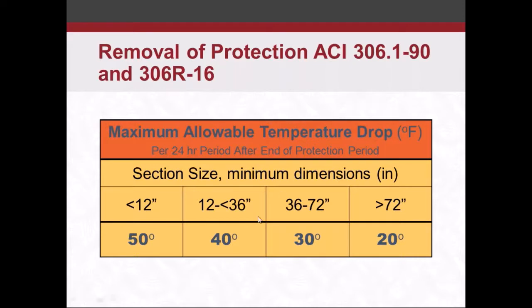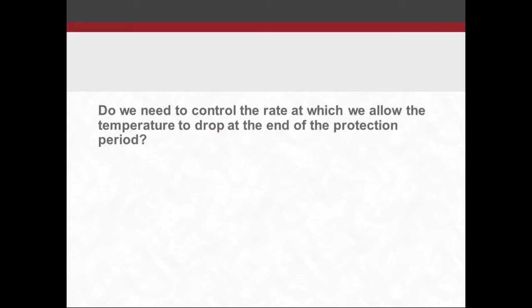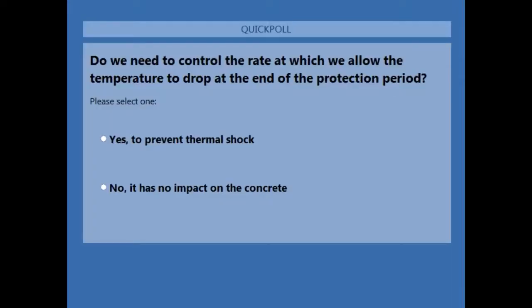Larger sections actually have a tighter requirement because on the inside, you're going to have a lot higher temperatures than you're going to have on the outside, and you don't want to have those huge temperature variations between the interior and the exterior of your concrete. That's really going to cause, or could potentially cause, some of that thermal cracking that we want to stay away from. So just know that we need to control that temperature drop over the 24-hour period. Oh yeah, and here's question number 3. Do we need to control the rate at which we allow the temperature to drop at the end of the protection period?